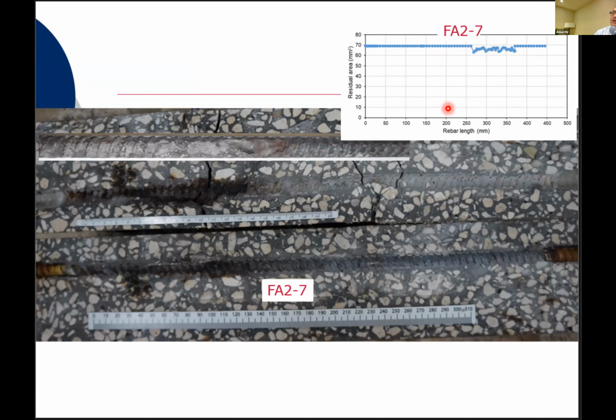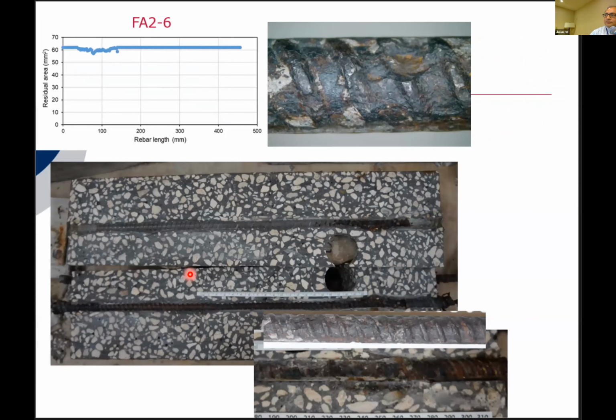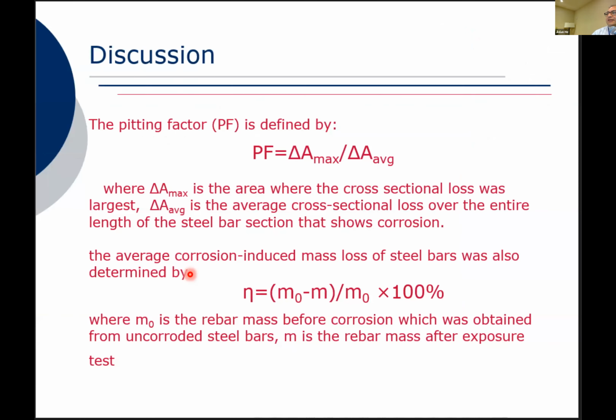And there is this region, I'm showing you this on the right, but actually with respect to this picture, the corroding side is here on the left side. So here is an additional example of that. We calculated what is called the pitting factor, but we did this slightly different from what is typically done. We obtained the maximum change in the area with respect to the average of the change in the area only on the corroding region. Others have calculated this with respect to the original diameter or the area of the rebar.